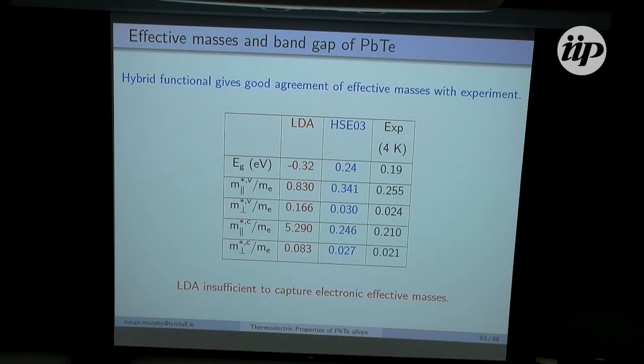Now, just to show you some of the values for the effective masses and how poor they can be for LDA. Taking this conduction band mass for LDA, it gives a value of about 5.29, compared to the experimental value of 0.21. Again, using the hybrid functional, we capture a value of about 0.246, in much, much better agreement with the experiment than the LDA case.